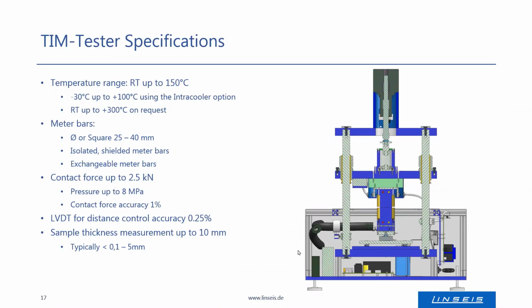Another fact here which I should mention is that the limit of 10 millimeter is set since for thicker samples, the radial heat losses will get a crucial problem, so that this sample setup does not make any sense. This is why it is recommended to rather measure thinner samples so that the heat losses on the side are not that large.